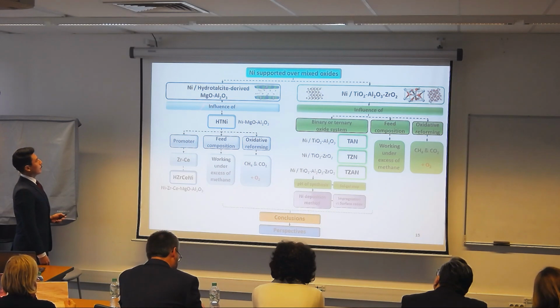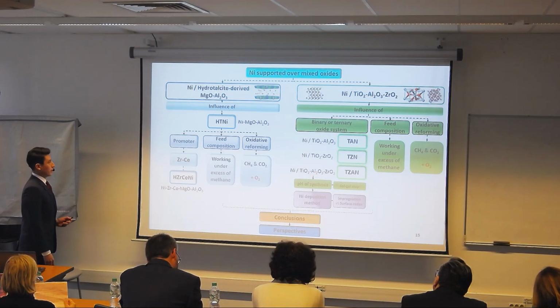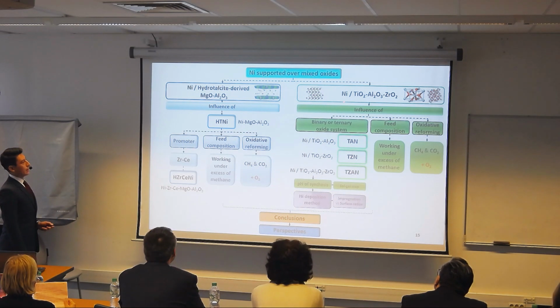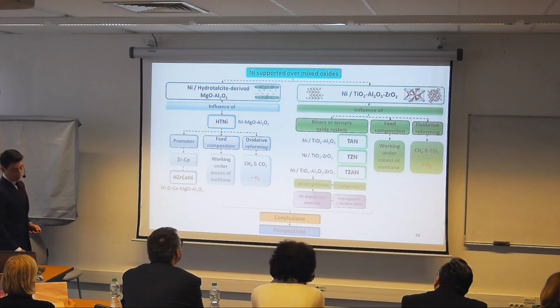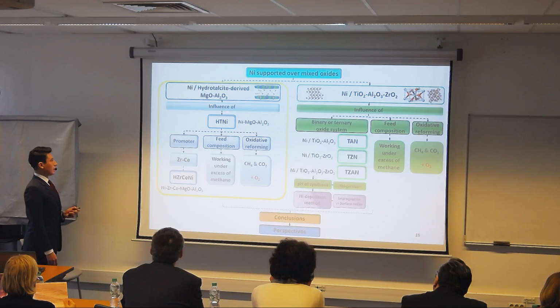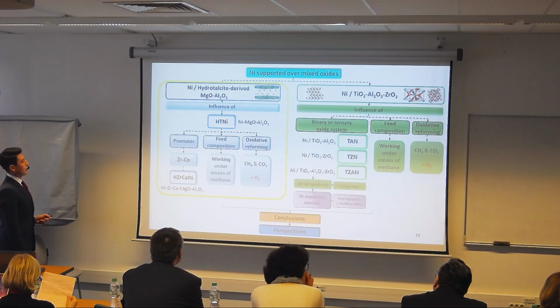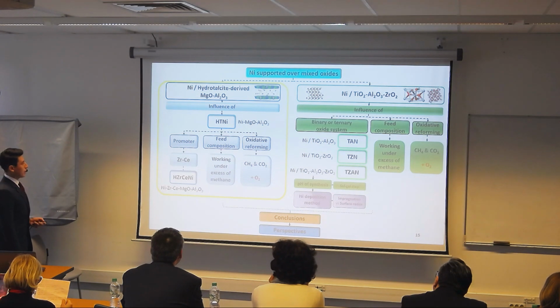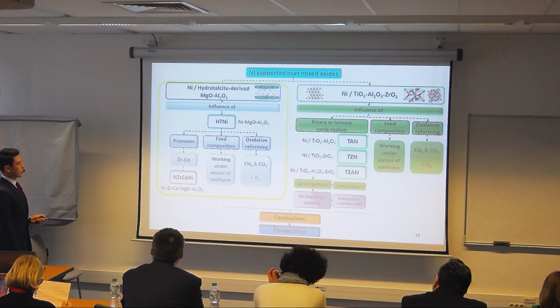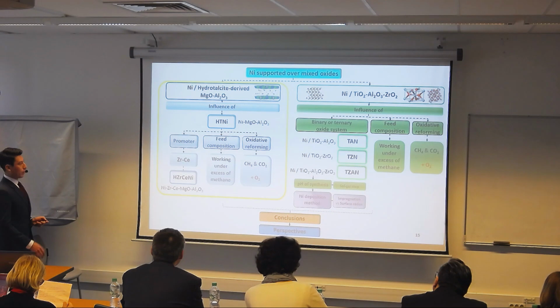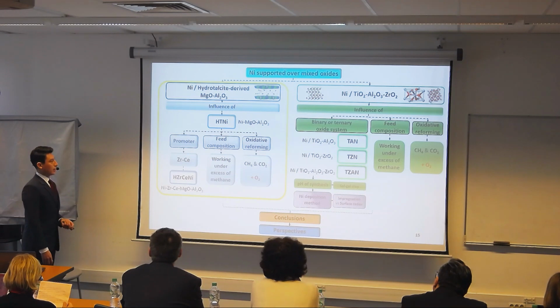I started with a nickel hydrotalcite-derived catalyst, and then I prepared a nickel titanium alumina zirconia catalyst. I'm going to start talking about this first group of catalysts. In the beginning, I tested nickel in this derivative catalyst, which mainly contains magnesium oxide and alumina. Then I'm going to present the results when we promote this catalyst with zirconia and ceria. These two catalysts were tested under excess of methane, that is biogas reforming, and then we tested them in the oxidative reforming.